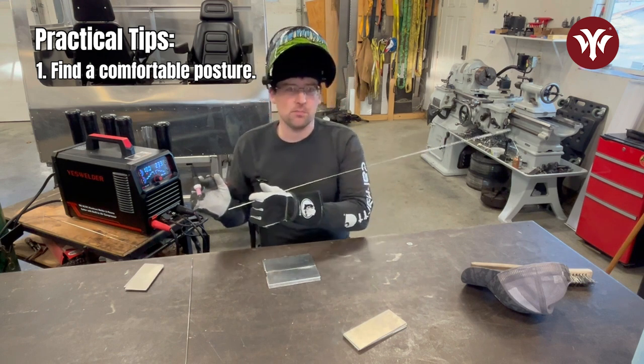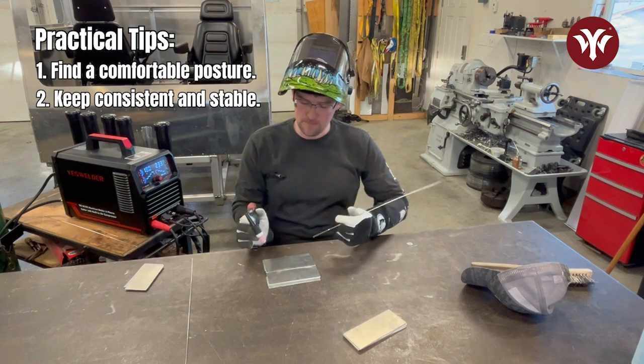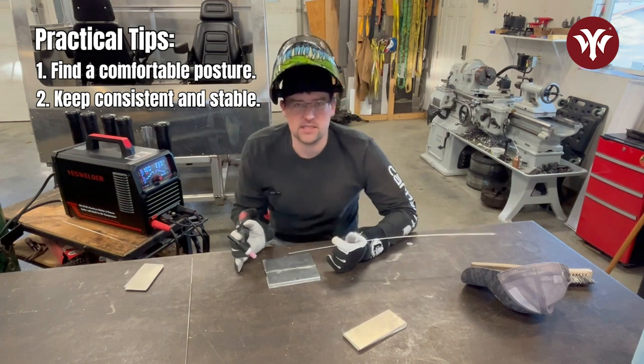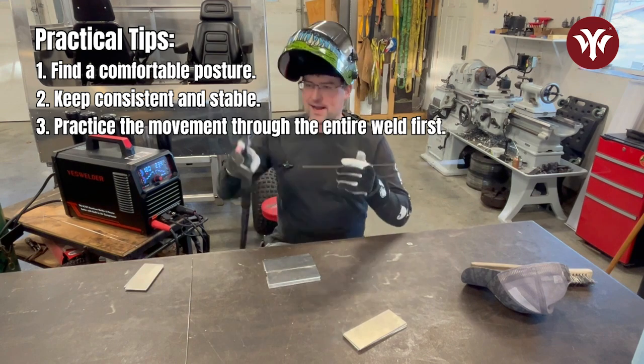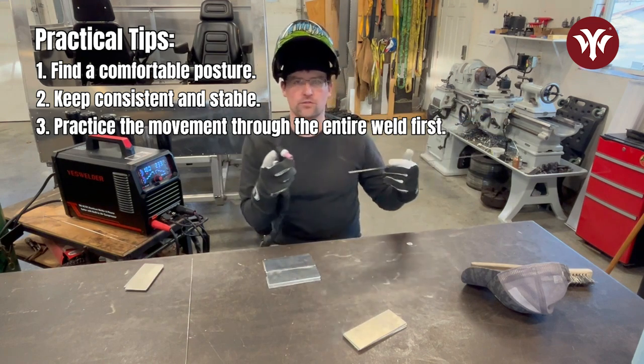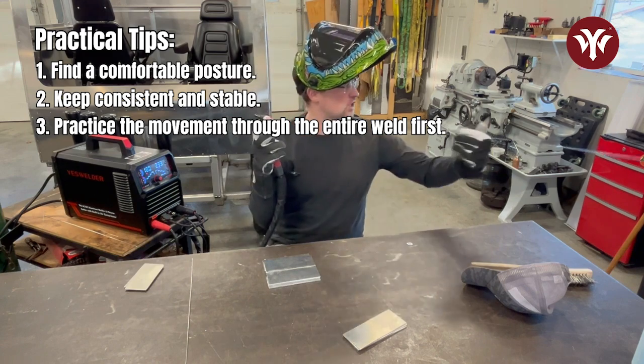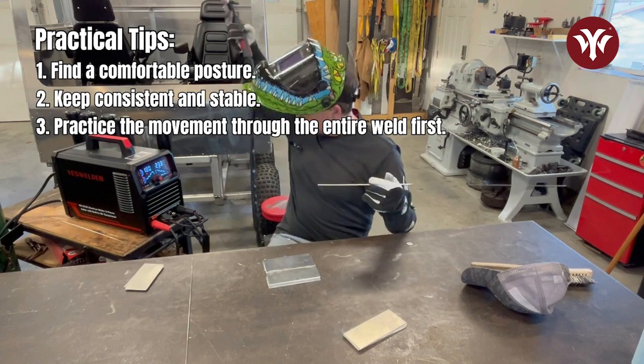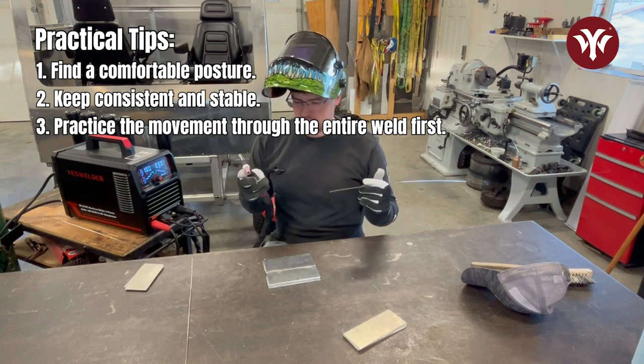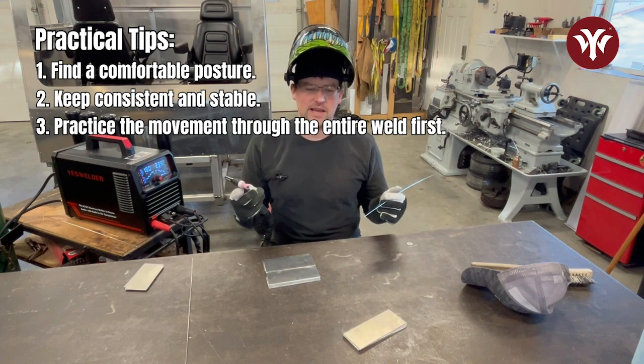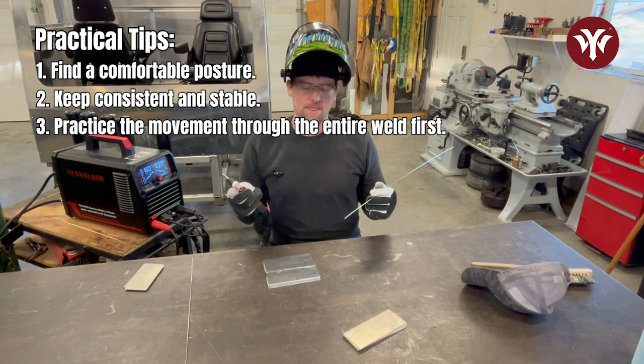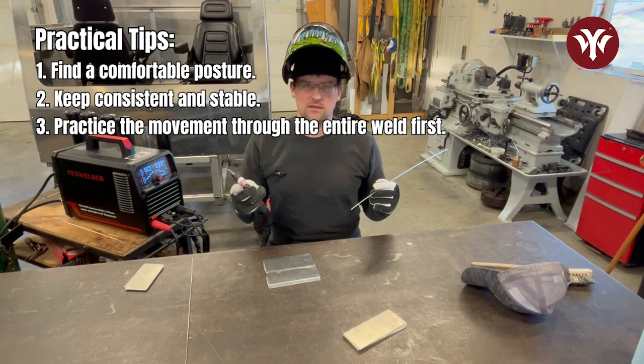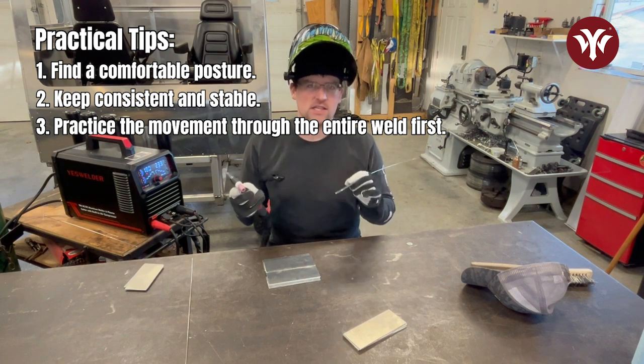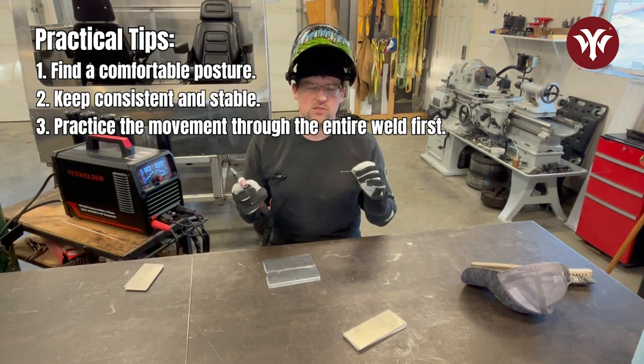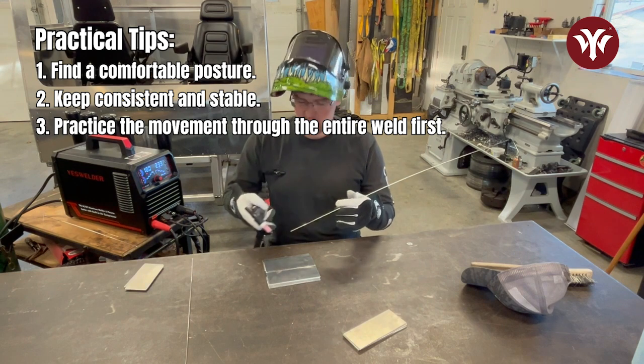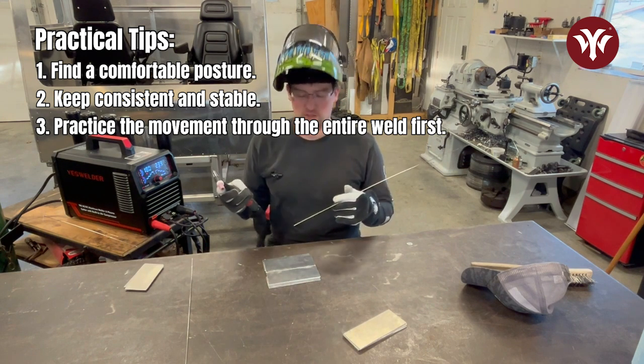So if you're looking for that nice, beautiful, straight stack of dimes weld, you need to be unbelievably consistent and stable. So always practice the movement through the whole weld first, so you know you're clear, start to finish. Your filler rod's not gonna hit anything, your TIG torch is loose enough. All these little things seem like they might be areas to skip, but if you're trying to weld those picture perfect welds, it is all these little steps that are gonna separate the home DIYer ugly looking weld from the professional.